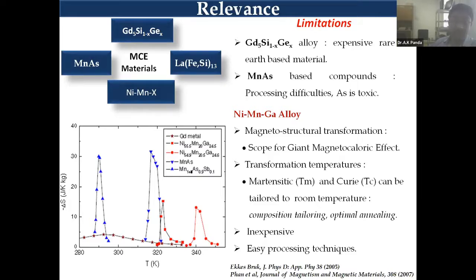Manganese arsenide, as I told you, is a bit toxic, so you would not like to have it. Nickel manganese gallium is something you would like to work on because there is scope of a giant magnetocaloric effect. Amongst all the materials, possibly nickel, manganese, arsenic, antimony are high, but because of their limitations, we do not want to go for them. In the case of nickel manganese gallium, there is scope of tailoring the properties, compositional tailoring, and not only that, you can anneal at different temperatures to raise the entropy. So you do not have any other limitations, and that's the reason there has been a lot of importance in working with nickel manganese based materials.